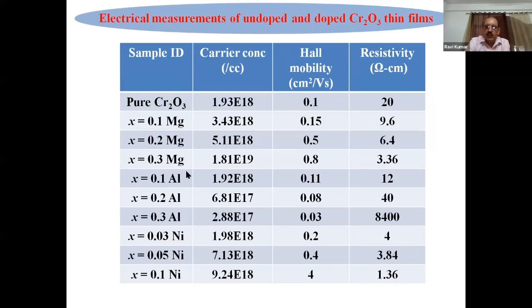In the case of aluminium, it is showing an insulator, whereas in the case of nickel, at low concentration, the resistivity is reduced to 1.36 ohm centimeter. The Hall mobility reaches 4, which is almost 5 times even the magnesium case. So it's a good Hall mobility we can consider at this time. So we can say that we prepared materials with p-type conductivity. Secondly, they have a good Hall mobility. They are good transparent materials. Resistivity is around 3.36 or 1.36 ohm centimeter. So this can be an achievement.